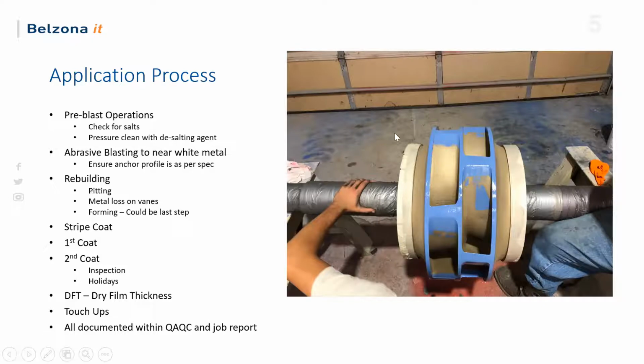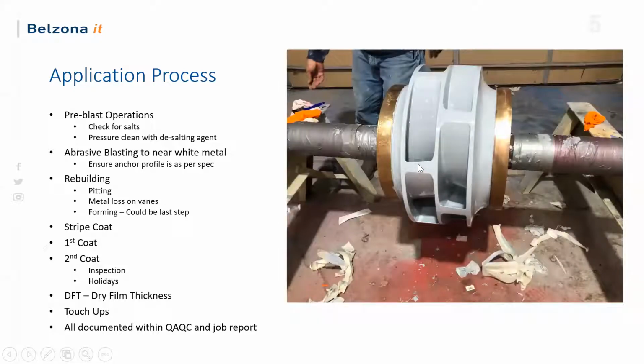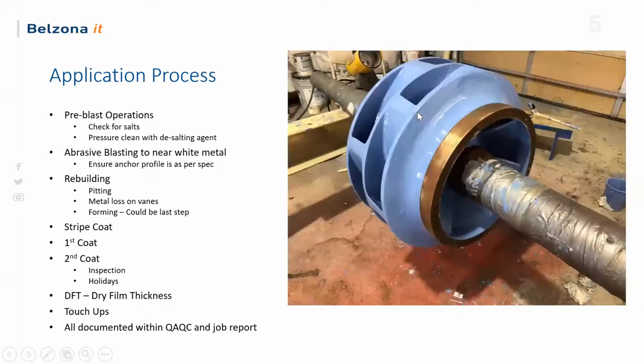Once you're done with that, this is what we call a stripe coat. Any sharp edges, corners, or welds get an additional coat so they have good coverage across the edge, because the edge is usually the toughest place to get retention, as it has a lot of surface tension. That's our stripe coat. Then you apply a coat to the whole substrate, and then you do a second coat. Once you do a second coat, you come back the next day and do a full inspection where you test for coating thickness, which has to be within spec, and you look for any misses, which can be done with a spark test or a wet sponge test.